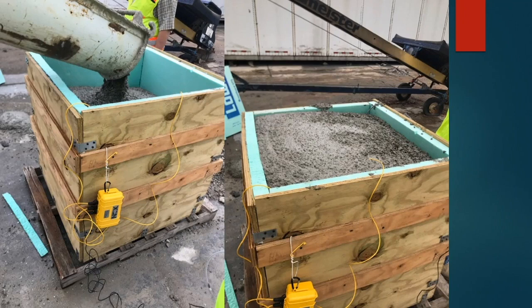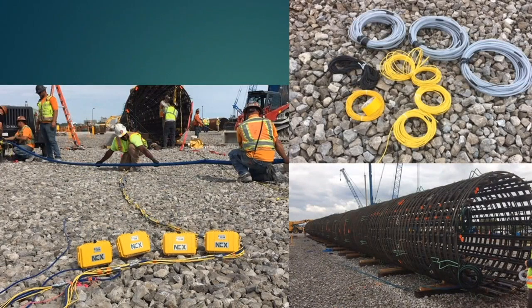And at that point, once we know that the mix design is capable of not blowing past our peak temperature, then we can use it in the field. And these are just some pictures of a large mass concrete job that we're currently on. We have lots of sensors that are going down inside a very large drilled shaft. The sensors are all strapped up to this giant cage that is then lifted and placed, put inside the hole, and it is a huge project.